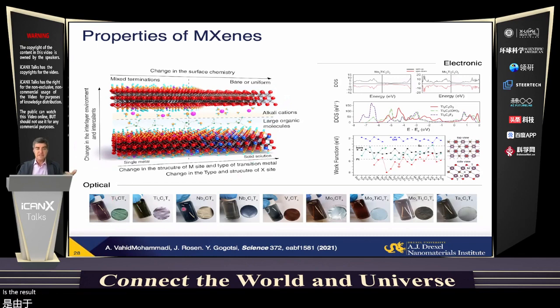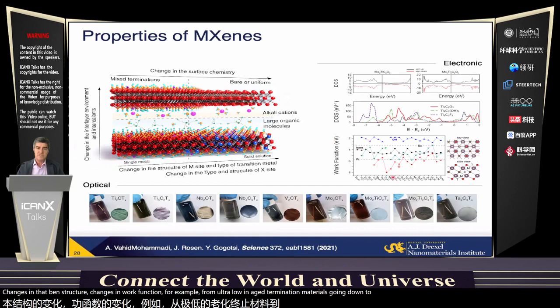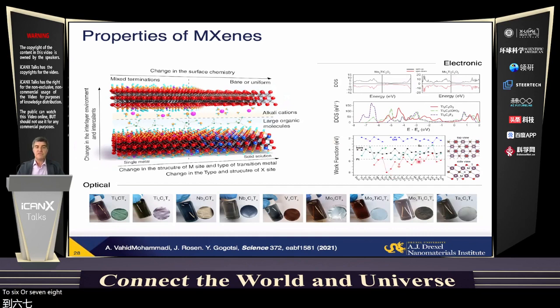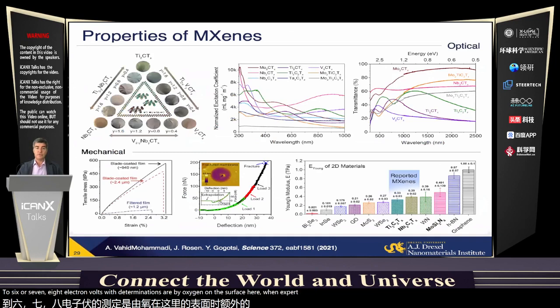As a result, you will end up with a variety of plasmonic colors in these materials, changes in the band structure, changes in work function. For example, from ultra low in OH-terminated materials, going down to 2 electron volts, to 6, 7, or even 8 electron volts with terminations by oxygen on the surface, where there's an extra electron atom. Moreover, we can mix those elements, making a solid solution, as I mentioned, on the X side and M side, and tune properties finely, getting high mechanical strength, getting plasmon resonance, covering actually the entire visible and much of the infrared range here.